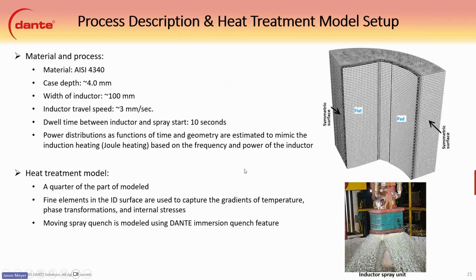Power distributions and functions of time and geometry are estimated to mimic the induction heating. Again, we use the Joule heating modeling here based on the frequency and the power of the inductor, and basically targeting the case depth that they requested here. So we used a quarter model, again, using symmetry as best we can.